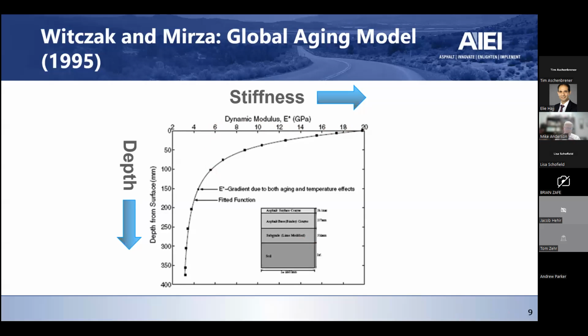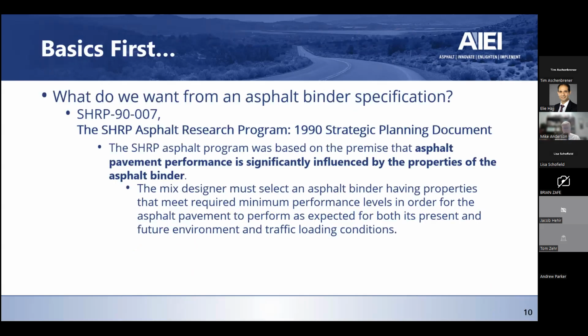That tells us that a lot of the aging happens early, near the top of the pavement surface. That makes sense because as you build a pavement, you've got air voids in the pavement, and air and water can get in through the top, and that oxygen starts diffusing, but it doesn't get as deep into the pavement structure itself. As a matter of fact, at some point, as you can see from this graphic, it really tails off where there's not much change at all. That's telling us that the oxidation rate is changing quite a bit, and there's not as much free oxygen to age the material. But at the surface, it can be quite extensive. So when SHRP was formed, this was the basis behind the PG specification.